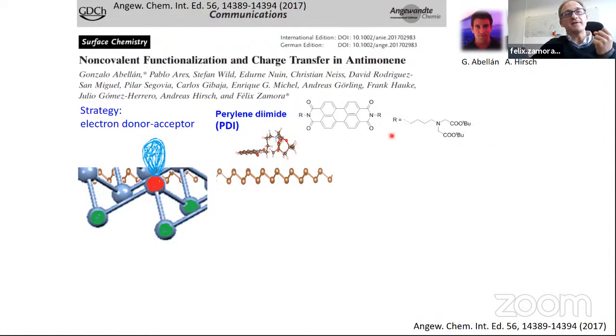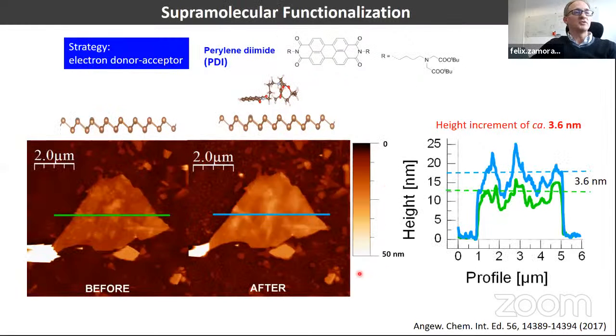So the idea here, in collaboration with Gonzalo Abellán and Andreas Hirsch, was to look for a molecule that is an electron acceptor. That is the reason why we were working with perylenediimide, this strange, long molecule. And then we did the following experiment. First, we produced by micromechanical exfoliation a single layer, or a few layers of antimony, located on silicon oxide. So this is the case.